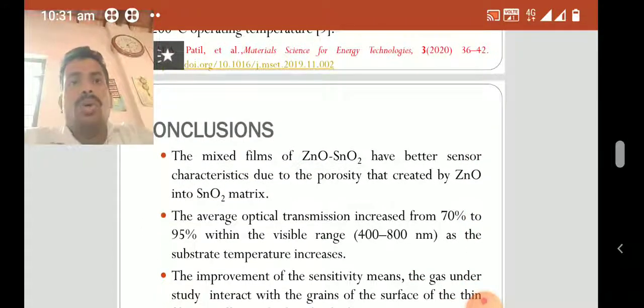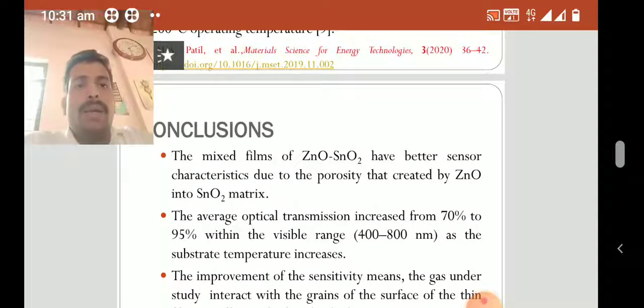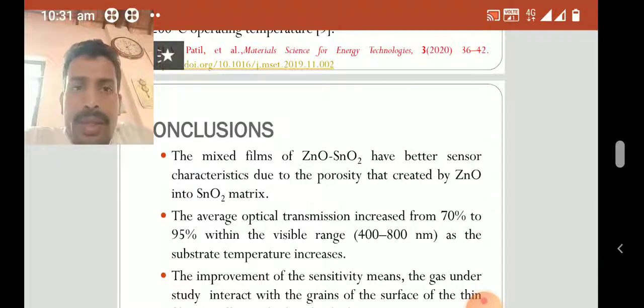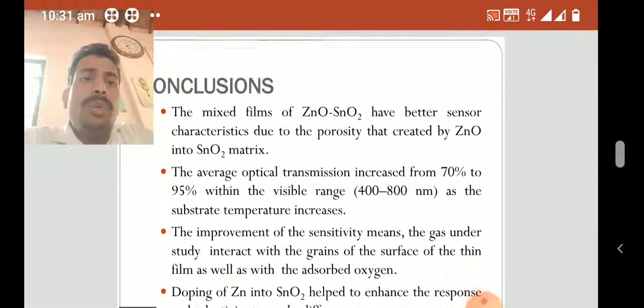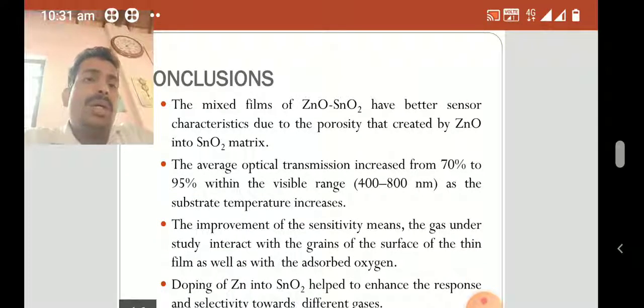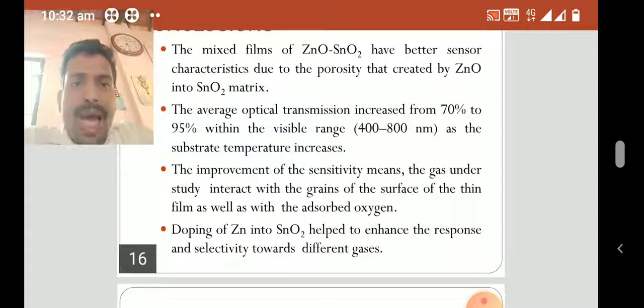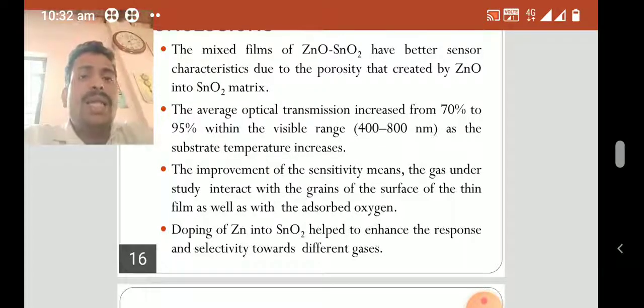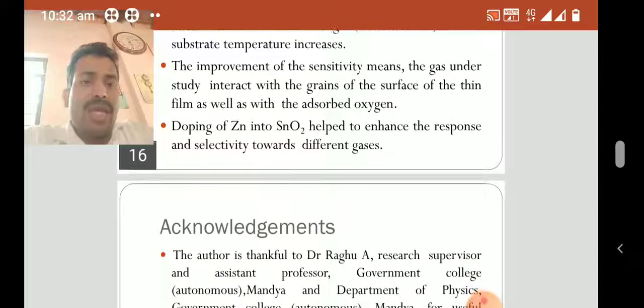So it is the time for conclusions. Totally, the mixed films of zinc oxide and tin oxide have better sensor characteristics due to the porosity created by zinc oxide in the tin oxide matrix. The average optical transmission increased from 70% to 95% within the visible range as the substrate temperature increases. The improvement of the sensitivity means the gas under study interacts with the grains on the surface of the thin film as well as with the adsorbed oxygen. The doping of zinc into tin oxide helped to enhance the response and the selectivity towards different gases.